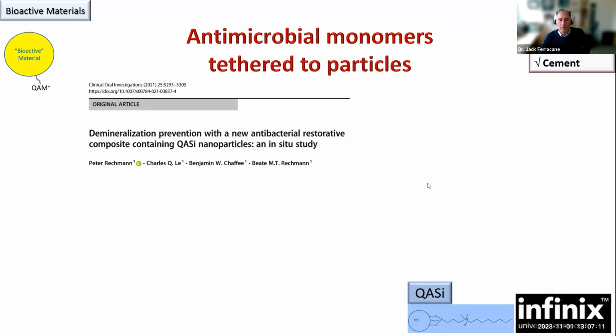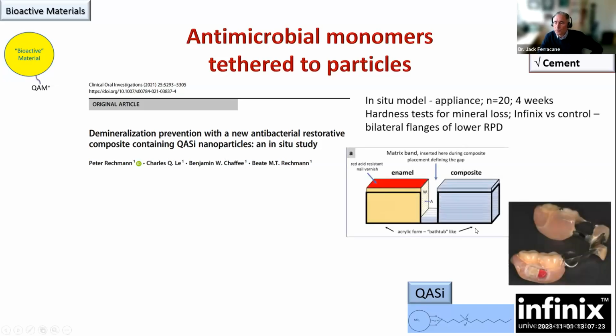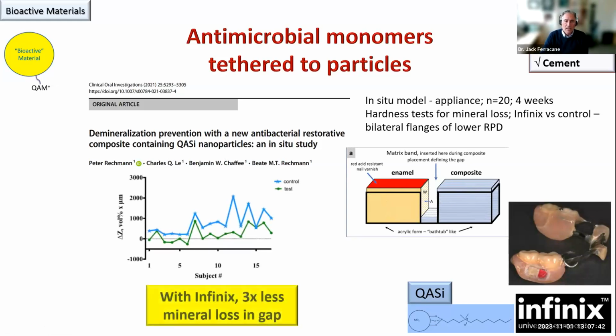So there was a nice study done by Peter Rechmann looking at demineralization prevention with such a material containing these, what they call QA silica nanoparticles. So the idea was to produce in this partial denture system, the composite material here, the enamel, and to see what kind of a lesion forms here when the bacteria is exposed to a material that contains the compound. And what they found was that with Infinix, this material that contained the QA-SI, there's 3 times less mineral loss in the gap than when it was exposed to a regular composite, which did not have this. So some clinical evidence that the molecules are actually doing something to the bacteria, not a complete elimination or reduction, stopping mineral loss, but at least a reduction.